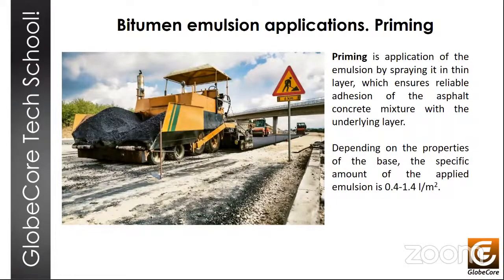All right, so extensive experience shows that the most effective use of bitumen emulsions is in the so-called cold technologies for the construction and repair of roads. So first, we'll talk about priming coats. Priming is the application of an emulsion by spraying it on the surface in the form of a thin layer, which ensures reliable adhesion of the asphalt concrete mixtures to the underlying layer.